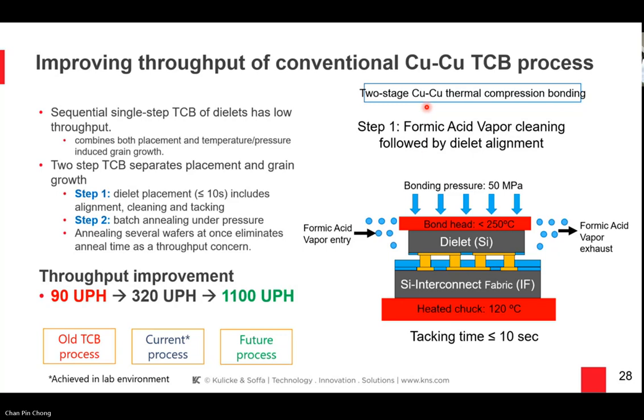When we started, we were doing this all in one step, and our throughput was about 90 units per hour. Then we went to this two-step process in the APAMA tool, and we were able to get about 320 units per hour. When we go to the Aptura tool with the two heads, we should be able to easily get to greater than 1,000 units per hour. At about 1,000 units per hour, this becomes a very attractive process for thermal compression bonding.